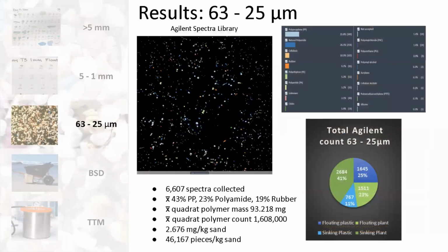In our much smaller size category that was sent out to Agilent, they were able to collect over 6,600 spectra, and our mean quadrant polymer mass that we removed before we sent out to them of those plastics was 93 milligrams. And the mean amount of these polymers in each quadrant was over 1.6 million pieces of these microplastics. It's a very, very startling figure. That's the extrapolated data from what Agilent processed, and per kilogram of sand, again, 46,000 pieces. You notice in this one that there was more material than the other 2 chambers as far as what was separated natural and synthetic wise, but still very good results using this process.